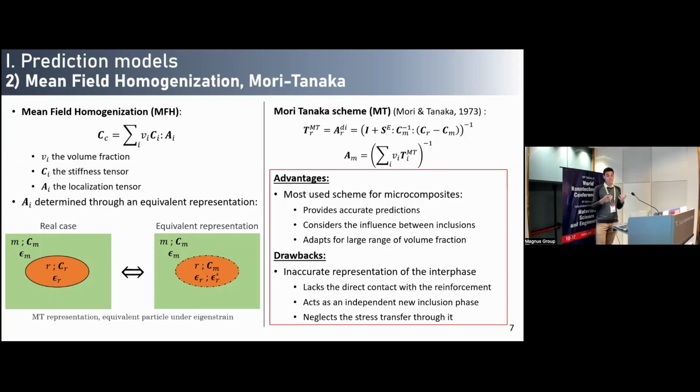But however, its drawback is that it's inaccurate in representing the interface, because when we add the interface in this model, the interface and reinforcement are just considered as two different phases, so there is no direct link between the two, and it doesn't consider the stress transfer that happens through the interface.